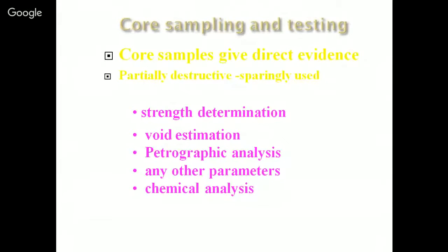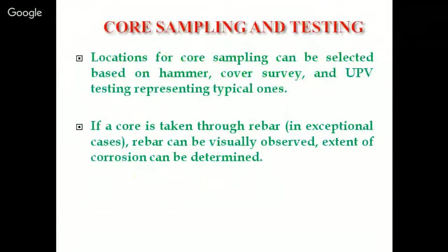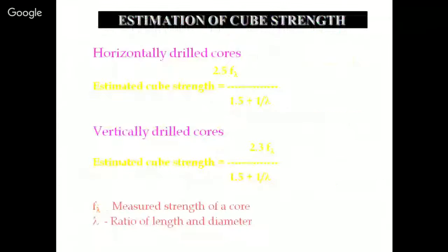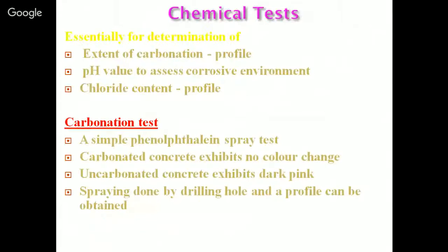If you have to find out chlorides and sulfates, because they also cause corrosion, you will be able to find out by chemical testing. Then we have to see how the core strength is estimated. Then you have the chemical test. Chemical tests are basically the extent of carbonation, because carbonation is the one phenomenon which causes corrosion in concrete. If we are able to arrest the carbonation in a concrete, we can prevent it, so assessing the extent of carbonation in any concrete is very important.